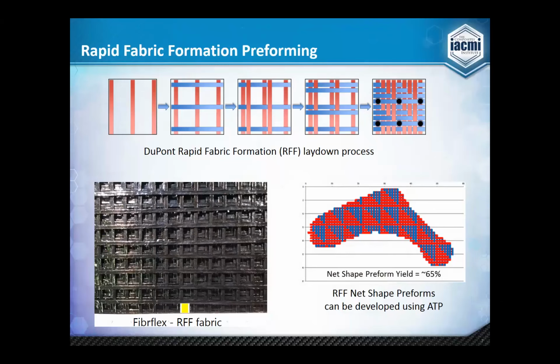Those are where the tows are thermally bonded, if you will, point bonded, to maintain the integrity of the preform. Now you can see on the lower left-hand corner, that's an RFF fabric made with our Fibrflex tow. And also, one of the beauties of this technology is that you can make near-net shaped products rather than having fabrics, which would conserve material considerably. And that's what we're showing in this slide here.